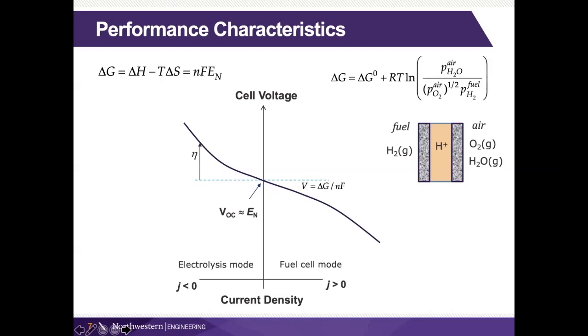In this case, the overpotentials are that difference in electrolysis mode, similar to what we had in fuel cell mode. So one thing that makes the electrolysis mode interesting is that this Gibbs energy, we can break it up into the enthalpy contribution and the entropy contribution. And so let's say that if we now compute the voltage associated with that, let's put it right here. And what's interesting about that is that this becomes the heat requirement in order to operate this reaction, because this reaction, electrolysis, requires heat in. So this is an endothermal reaction. So the amount of heat that we get from the inefficiencies of our system is defined by this overpotential.